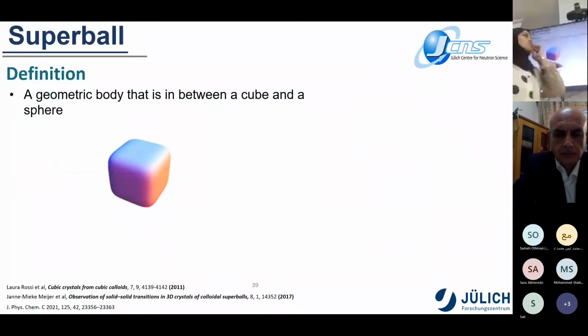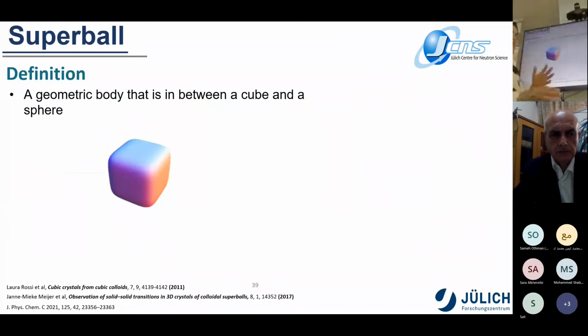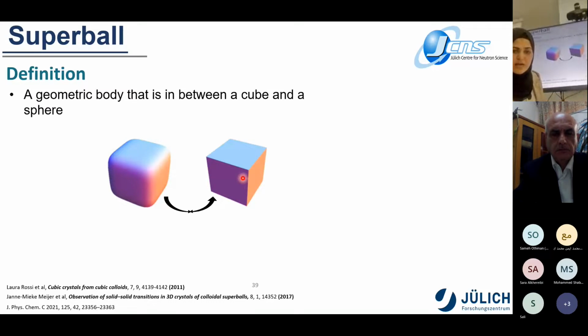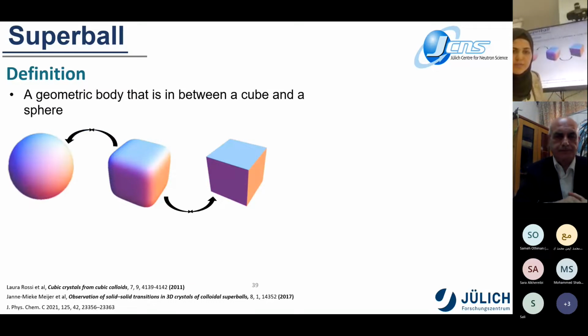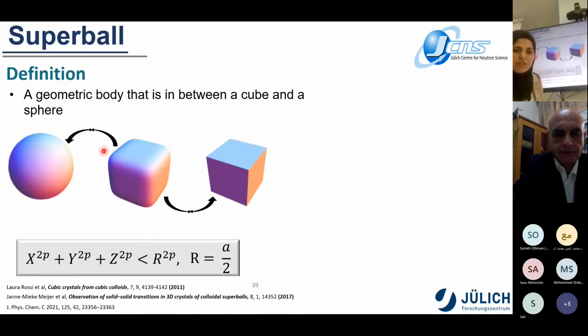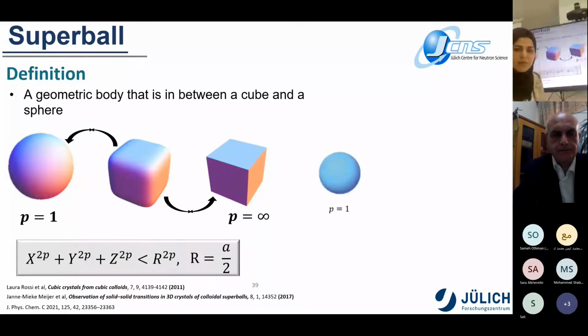Now it's time to introduce what we mean by a superball. A superball is a geometric body located between a cube and a sphere, which was the main research for me during my postdoctoral position at Cologne. The equation that defines this shape is as follows, where p is the parameter that defines the rounding of the edges. If p goes to infinity, then we have a perfect cube with defined edges, and when p equals 1, we end up with a sphere.